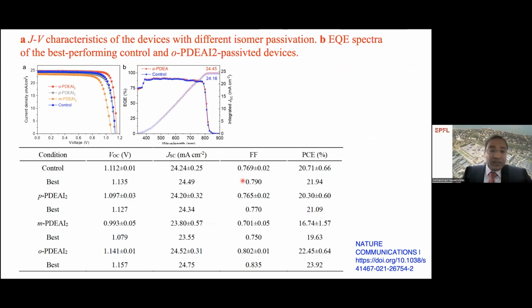Using this configuration, as a control, we have a 21.94% efficiency. And the para-substituted one gives us 21% efficiency. And the meta-substituted one is lowering the efficiency from 21.9 to 19.6. And the ortho one is increasing the efficiency, reaching very close to 24%. So what is happening here is that we don't have to really form the two-dimensional perovskite with the lead. Even these organic cations are sufficient to passivate the interface and give high efficiencies.